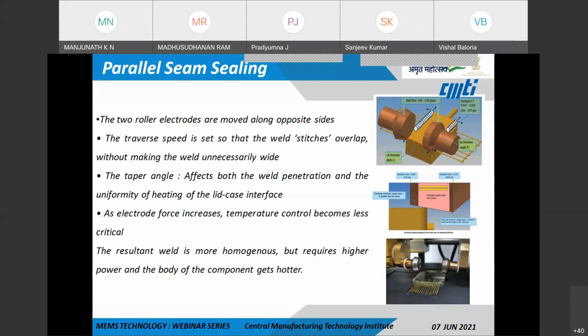As the electrode force increases, the temperature control becomes less critical, but the contact resistance goes down and more heat is conducted between the lid and the package. So this is how more heat is conducted between the lid and the package and the welding happens. The resultant weld is more homogeneous but requires higher power, and the body of the component gets a bit hotter.